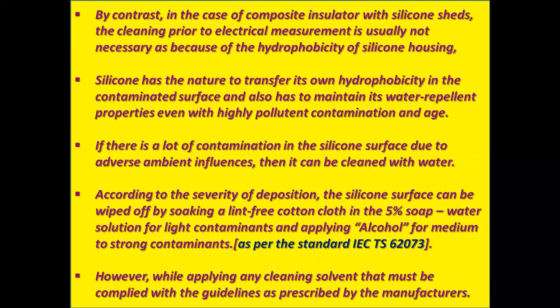If there is a lot of contamination on the silicone surface due to adverse ambient influences, then it can be cleaned with water. According to the severity of deposition, the silicone surface can be wiped off by soaking a lint-free cotton cloth in the 5% soap water solution for light contaminants and applying alcohol for medium to strong contaminants, as per standard IEC TS 62073.